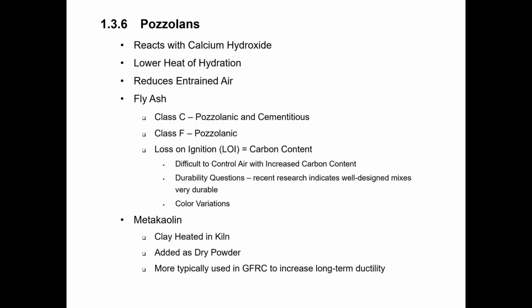GFRC tends to have very high cement contents. That makes for a very strong material, but it also makes for a material that over the long term tends to become brittle and has a greater potential for cracking. It's not a very ductile material in the long term, but by using a material like metakaolin, that helps to increase the long-term ductility of the GFRC so that it does not become embrittled as quickly.